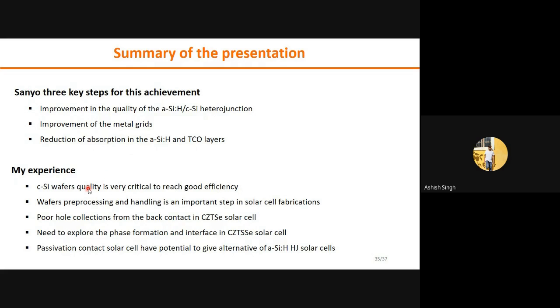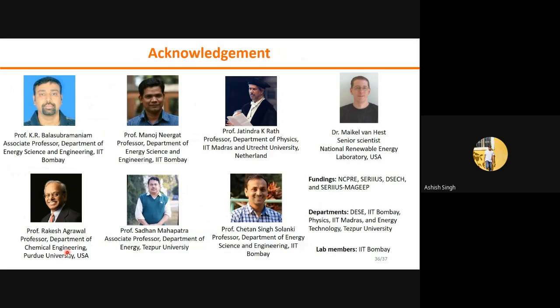This is the summary from the second section. As per my experience, I found crystalline silicon wafer quality is very crucial to get good efficiency, and wafer processing and handling is an important step in the fabrication of solar cells. In CZTSe based solar cells, poor hole collection is the main reason for the lower efficiency, and we need to explore the phase formation and the interface between the absorber and the different layers of CZTS. In addition, I can say the passivated contact solar cell has the potential to be an alternative to the amorphous silicon heterojunction solar cell.